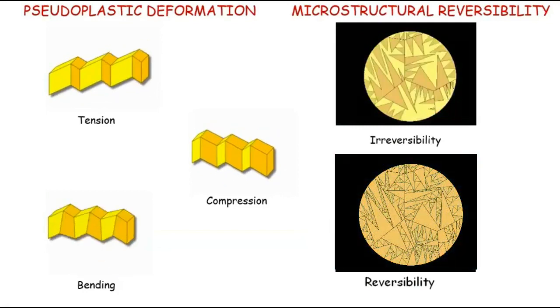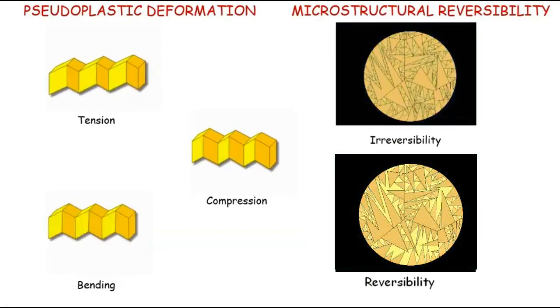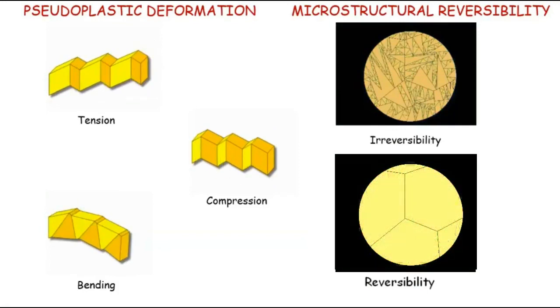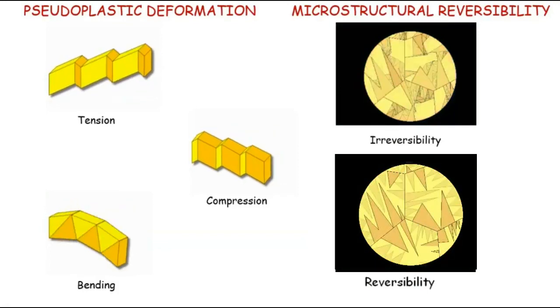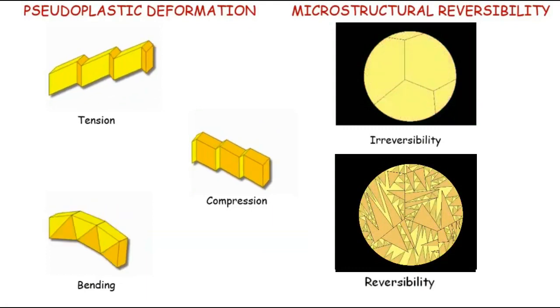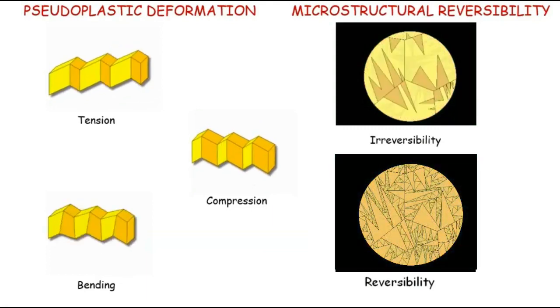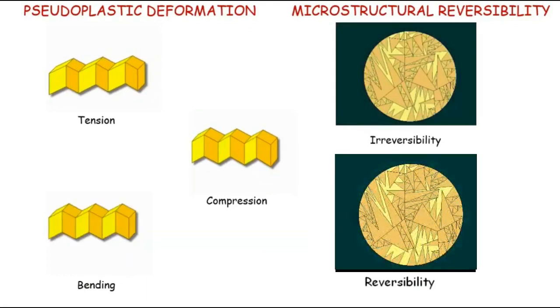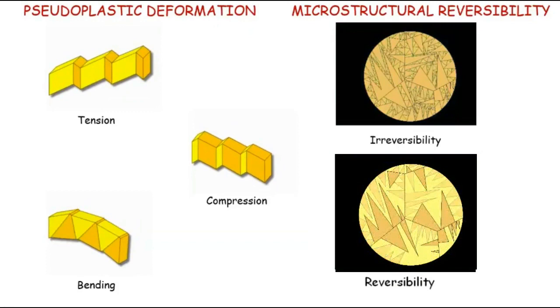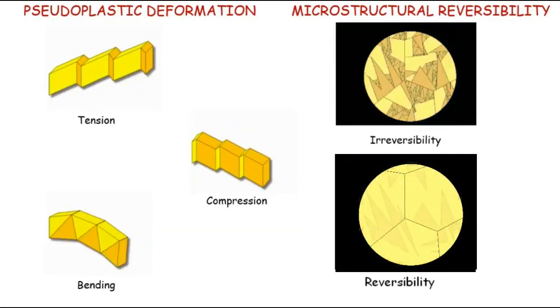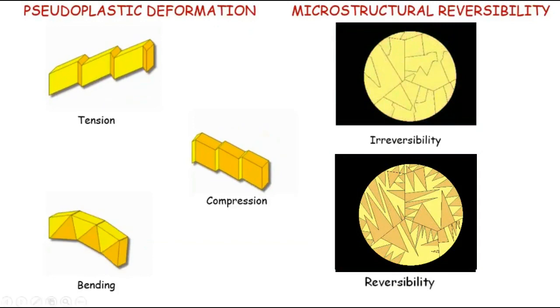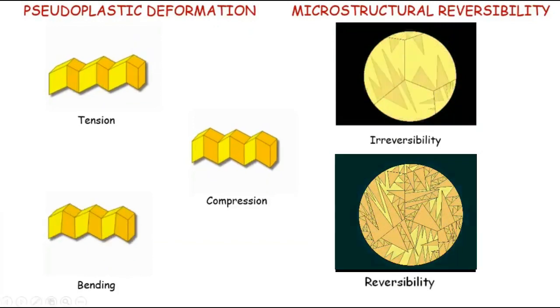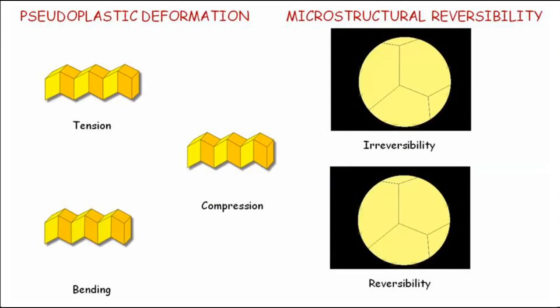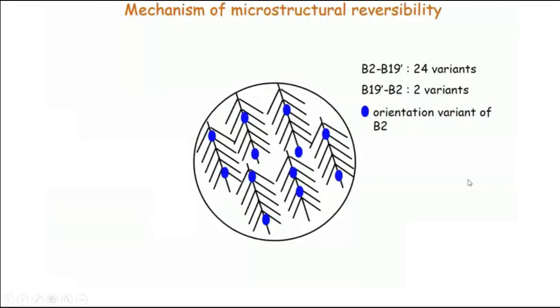So you have two situations here. One is pseudoplastic deformation, in which you have a deformation that doesn't have any dissipative mechanism. You can just change the shape and nothing much happens in terms of the energy landscape. All you've done is expend energy through friction. You move the interface and you lose something in heat. Nothing much else has happened. But in the microstructure reversibility, whatever you have done and whichever way it's arranged, it gets back to the original crystal. So these two things are the phenomena behind the shape memory. I hope these animations have conveyed that point.